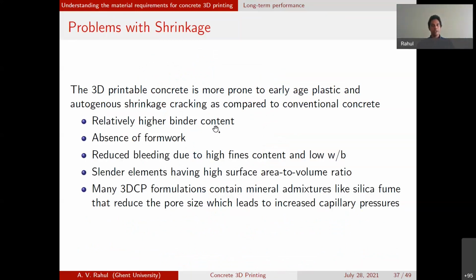Now, printed concrete doesn't have coarse aggregate most of the time. That means you often have a high binder content. The high binder content makes it a very good candidate for shrinkage cracking. So this is also something that we need to look at. But again, there's not that much literature on the shrinkage cracking potential of printed concrete. For normal concrete, the formwork protects the concrete from the external environment, so it's not exposed immediately to the external environment.